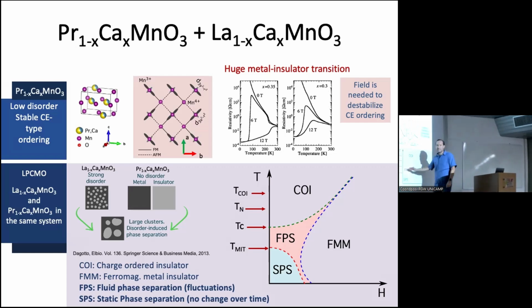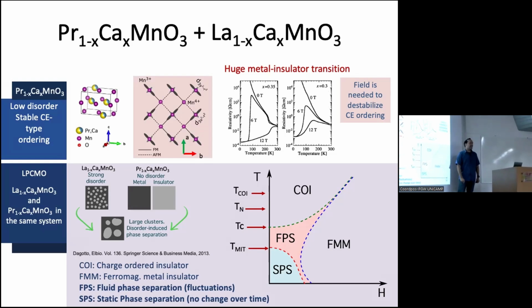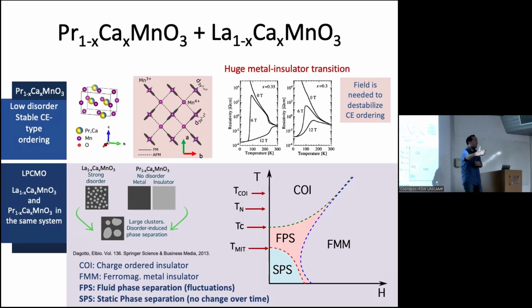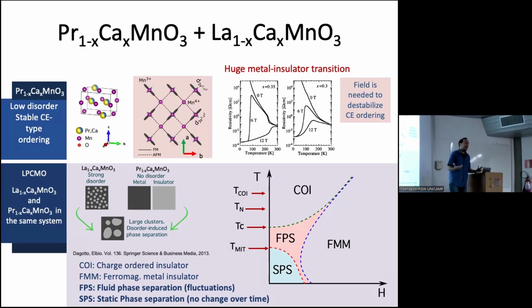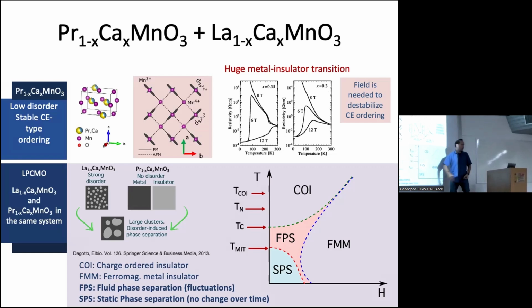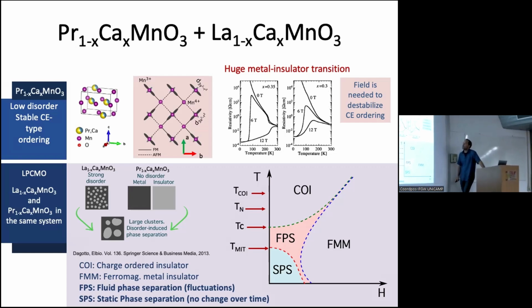And that is something very interesting. And of course, it has a bunch of dynamic properties because of the nature of a fluid. And then when the metal insulator transition kicks in, then you have a solid. So now whatever remains of this liquid, it freezes and it solidifies. I'm speaking about magnetism. And then those domains are somehow frozen to the lattice and they don't move anymore. There is no dynamics, okay? And this is quickly what I'm going to show you right now.